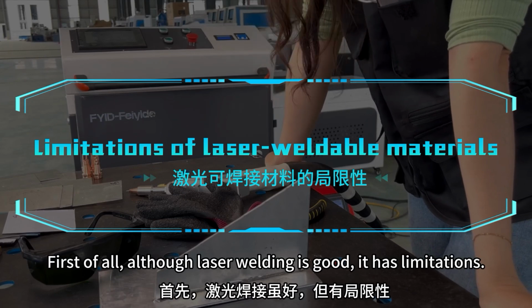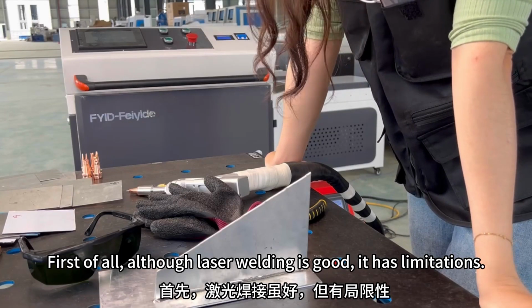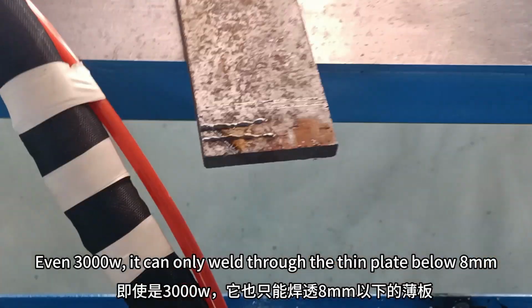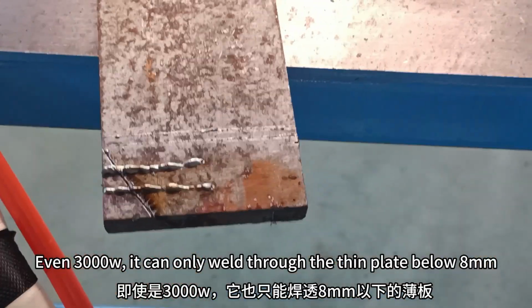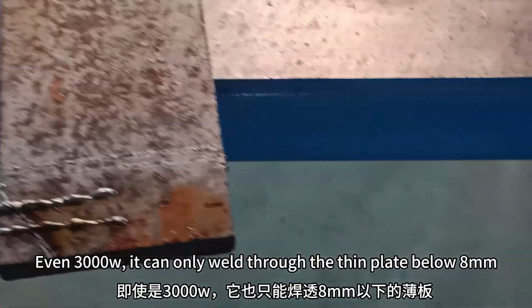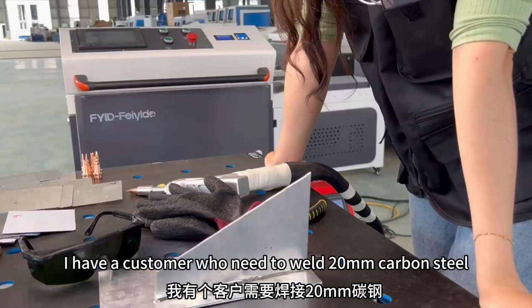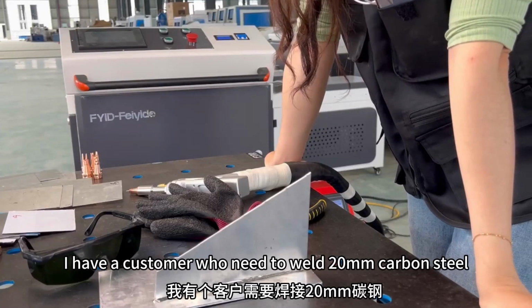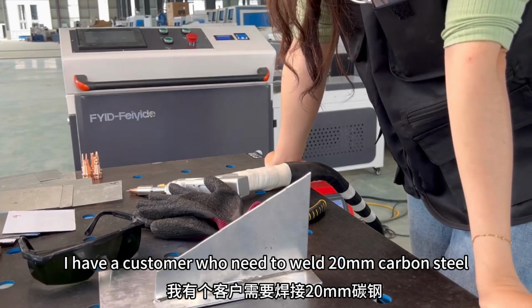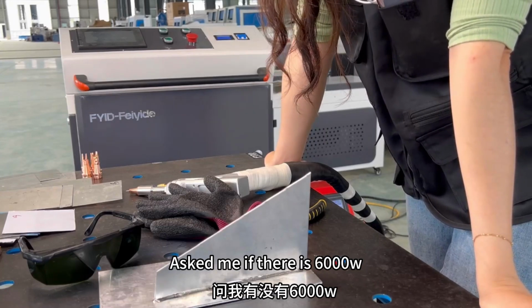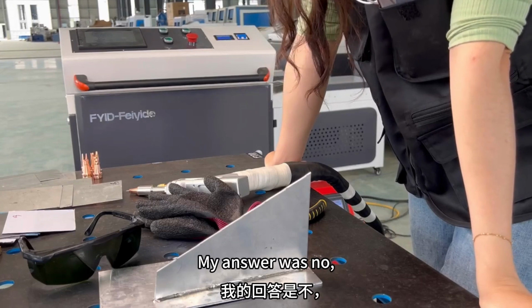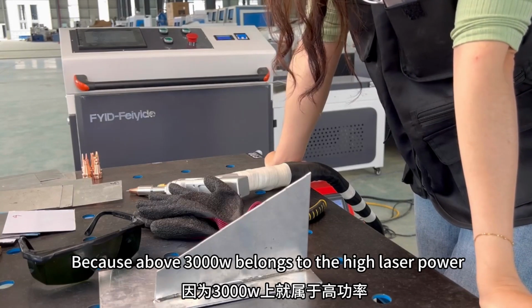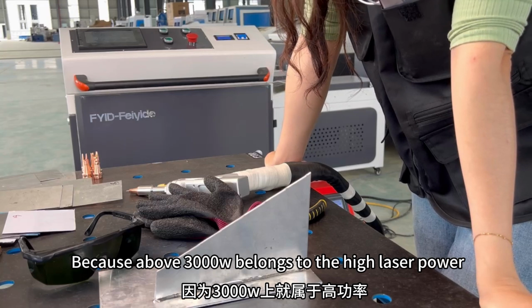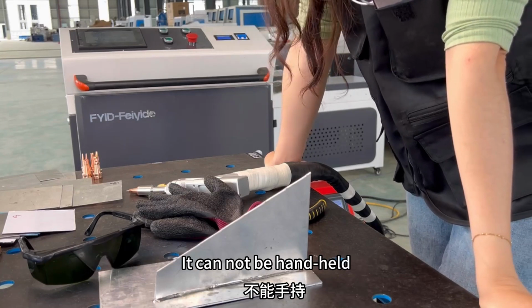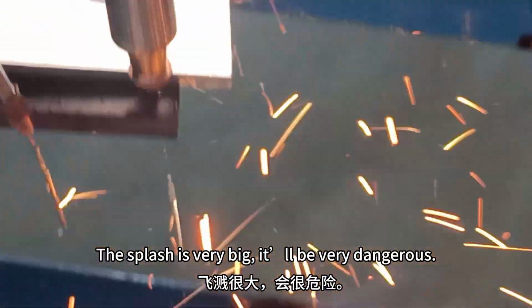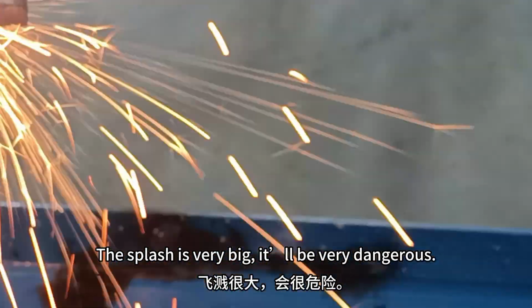First of all, although laser welding is good, it has limitations. Even at 3000 watts, you can only weld through thin plate below 8 millimeters. I have a customer who needs to weld 20 millimeter carbon steel, asking me if there is 6,000 watts. My answer was no, because above 3,000 watts belongs to high laser power. It cannot be handheld. The splash is very big, and it will be very dangerous.